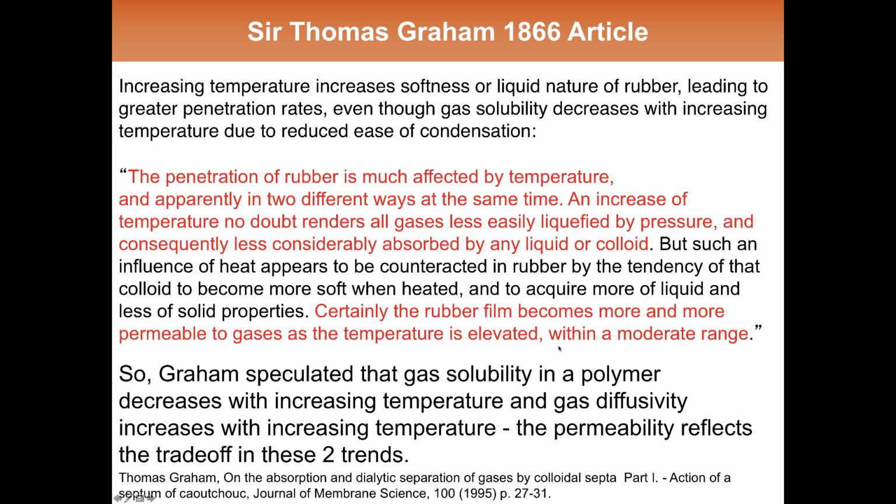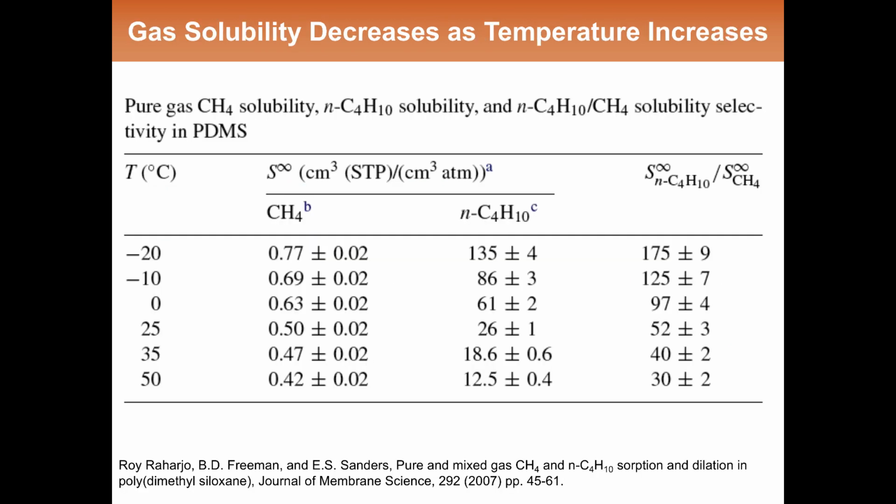And this can only mean, within the context of the solution diffusion model, that the diffusion coefficient must be increasing with temperature. The permeability, which includes both of those, reflects the trade-off in those two trends. And we see that very often in the literature and in the experimental work today. And it was first observed a long time ago.